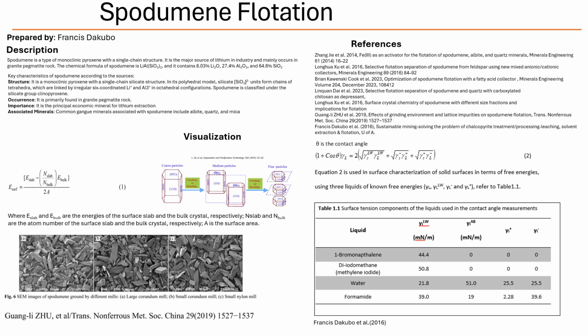And I saw mentions of using collector mixtures, not just one type. Yes, that's another strategy. Sometimes combining different types, say an anionic collector like NaOL, with a cationic one or with a non-ionic one can give better results than either one alone. Why is that? Teamwork. It's thought to be synergistic. Maybe they pack better on the surface together, or one helps the other attach, leading to stronger hydrophobicity or better selectivity against the gangue minerals. The exact mechanisms are still being researched, but mixing collectors can be effective.